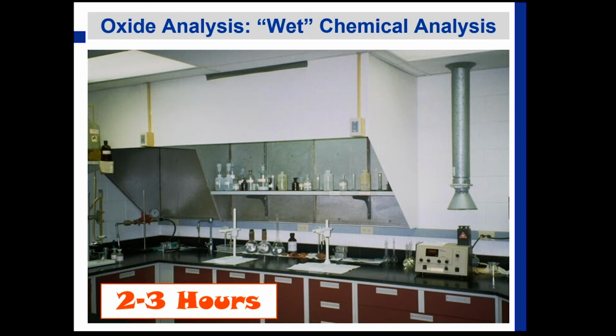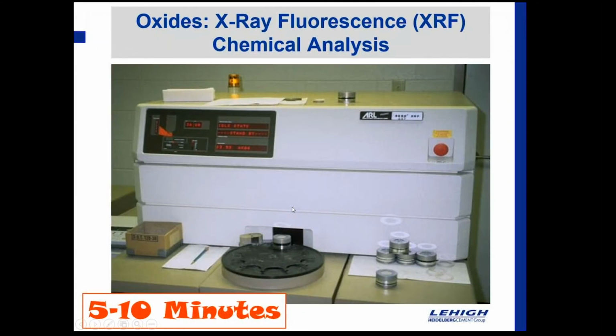And at about 2 or 3 hours, I can give you a pretty solid, pretty accurate breakdown of the oxide composition of that cement. But in 2 to 3 hours, there's been a lot of cement made because those mills don't stop while I'm in here running this chemical analysis. So what just about everybody would do these days, they do X-ray fluorescence for their chemical analysis.